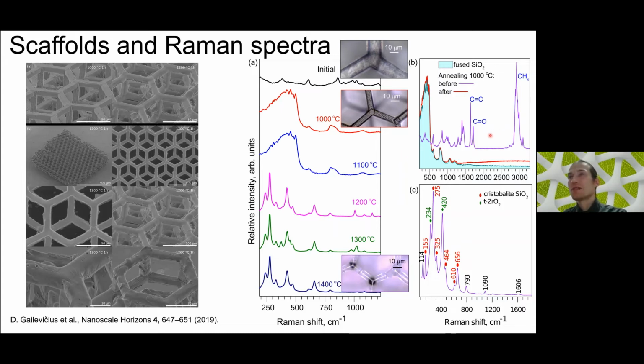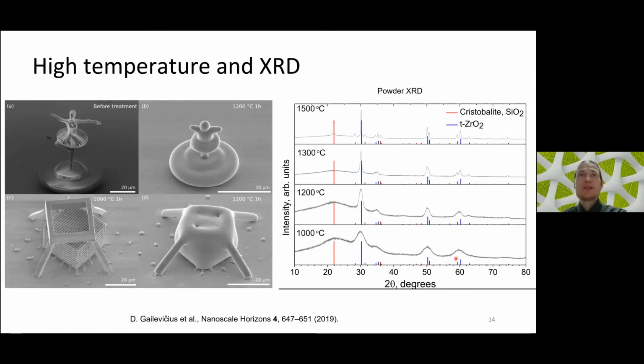Okay, so this is just the proof that the carbon, which was responsible for polymerizing the structure, eventually can be evaporated, and the downscaled structure is purely inorganic. The temperature can be too high, yes, if we go for extended periods and for some specific structures, so we can shrink too much or lose fidelity, and even though we see the dancer becomes a sumo dancer, or the template becomes just a cube, again it can be exploited for some useful applications like for microoptics, since the surface smoothness can be increased by simply adjusting the temperatures.